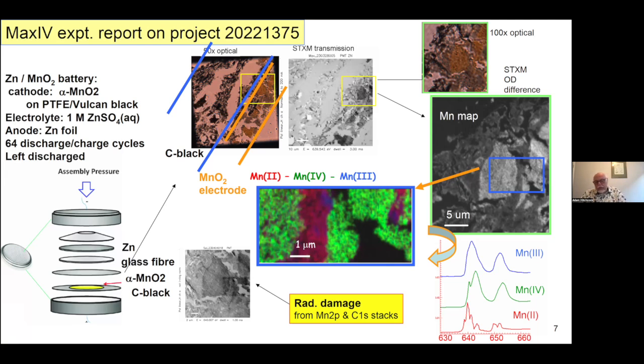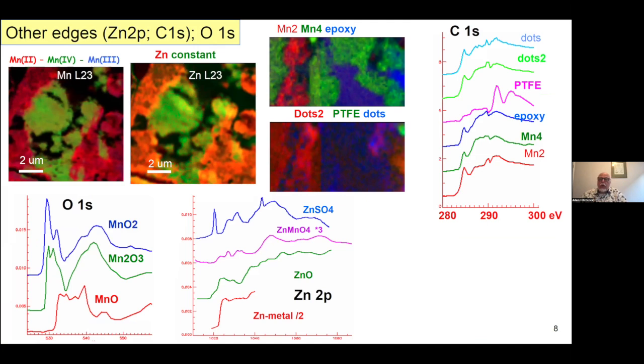analytical measurements they're making. So just one other point, you don't have to only use the one edge you target. And in this system, it turns out that the oxygen 1s is as able as the manganese edge to differentiate the oxidation states. So this is something to keep in mind, particularly when you're going into a project. It's really useful to think broadly about the sample and maybe do some exploratory measurements at other edges, which may reveal something interesting, even though that's not how you've initially planned the measurement.